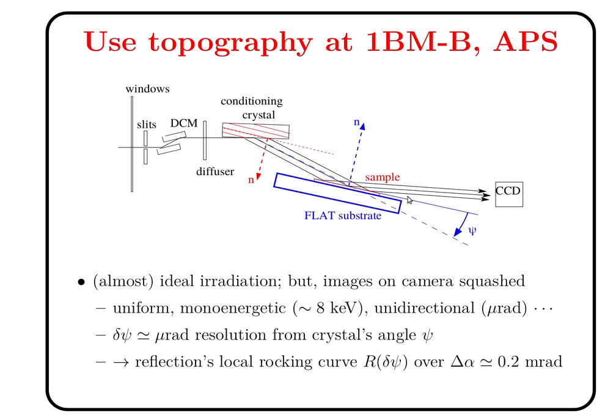And we can see that very accurately by changing the angle here under which the crystal sees the X-rays, and that makes the reflection change as a very sensitive function of the angle psi here. Typically psi is done in steps of 2 microradians over a range of like 0.2 milliradian, not very small range.